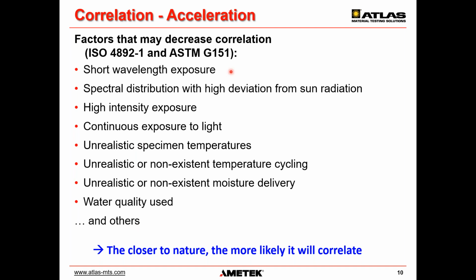However, if you attended last week's seminar on acceleration, you might remember that especially the first 5 of these influencing factors are the factors which are actually used for acceleration, to speed up aging, to speed up testing. And this shows, in principle, as soon as you accelerate, you may decrease the correlation. So you always have to find the balance between acceleration and correlation to get realistic results. But basically, the closer to nature, the more likely it is that the results will correlate. But you lose, of course, acceleration. So it's always, again, a balance.